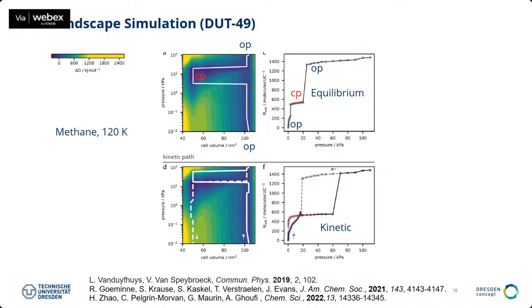Nowadays, it's possible to screen the whole energetic landscape of these materials. So here on the y-axis, basically, we have the pressure, and on the x-axis, we have the cell volume. And you can calculate all the energetics. So blue, the deep blue, is the energetic minimum, basically. And the green and yellow are the very high energy areas. And if you would only stay in the energetic minimum, you would go from the OP form. When you increase the pressure, so we start here, we go to the CP form, here we have the contracted form, and then we would go to the OP form again. So this would be the equilibrium situation when you only go to the lowest energy. But reality does not always follow the equilibrium.